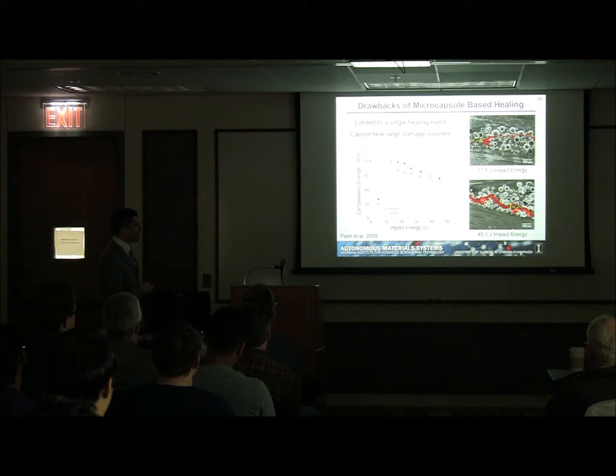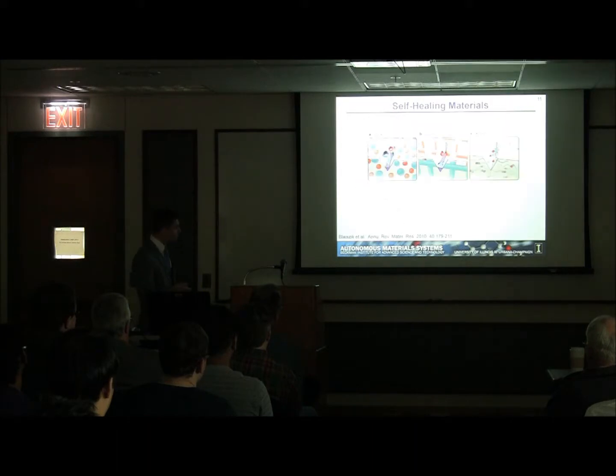And the reason for that is at low impact energies, the damage separation was small enough that we had enough volume of healing agent to fill the damage. However, at higher impact energies, the crack separations were too large and the capsules could not fill the damage.